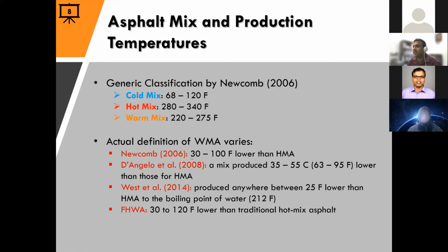Newcomb himself says 30 to 100 Fahrenheit lower than HMA is your warm mix. D'Angelo said 35 to 55 Celsius lower than HMA. West et al. said 25 Fahrenheit lower than HMA, all the way going down to the boiling point of water. FHWA, on their warm mix asphalt website, defines it as 30 to 120 F lower than the traditional hot mix. So basically, there are a lot of definitions. So what is warm, right? If you go to the industry or go to the experts, they will say that anything lower than 300 Fahrenheit, maybe 275, we're going to talk about that as warm. So the industry itself has not agreed on a single definition.